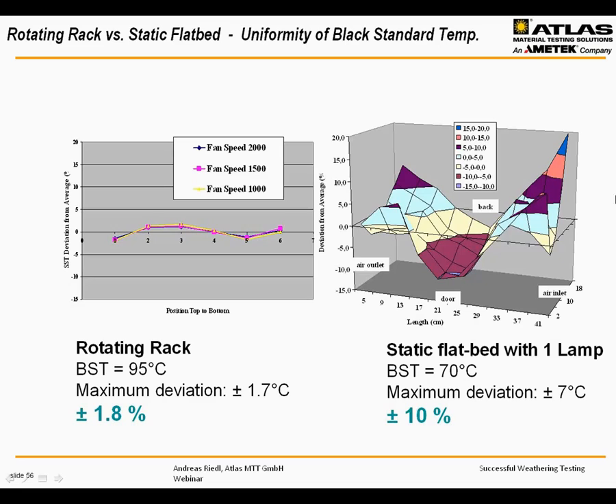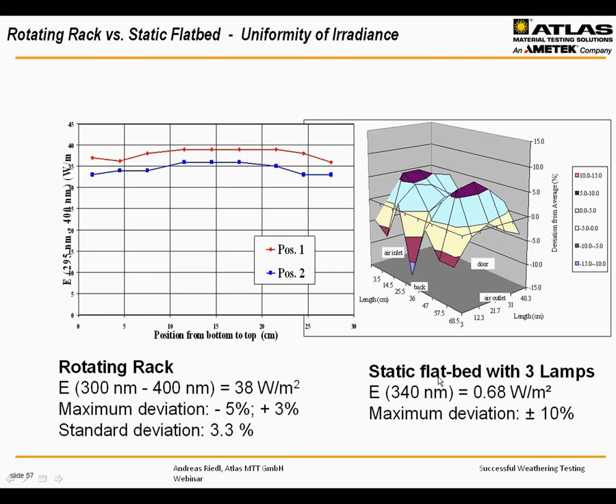What I would like to show you is that the rotating rack instruments provide a much better uniformity in temperature than the static flatbed instrument. The same applies for irradiance. That's the same with irradiance, 10% compared to 3 to 4%, which is, I would say, a world in between. And if you know that the material's degradation is very sensitive to very small changes in temperature and very small changes in the UV cut-on or in the radiance level, then you know how dramatic these differences are.